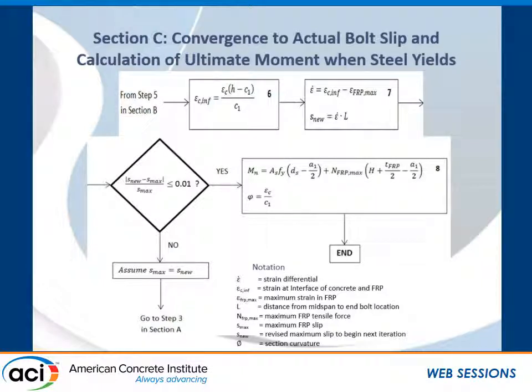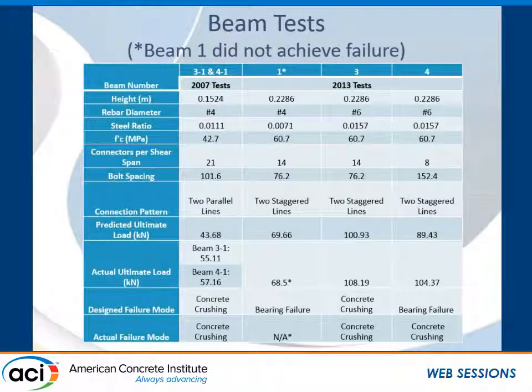Now, we had 5 7.5-foot long simply supported beams that we tested in 2007 and 2013 that we used to investigate the accuracy of our analytical method. All beam cross-sections were rectangular, either 200 by 150 millimeters for the 2 beams tested in 2007, or 200 by 225 millimeters for the 3 beams we tested in 2013. So we were looking at wide, shallow sections here.